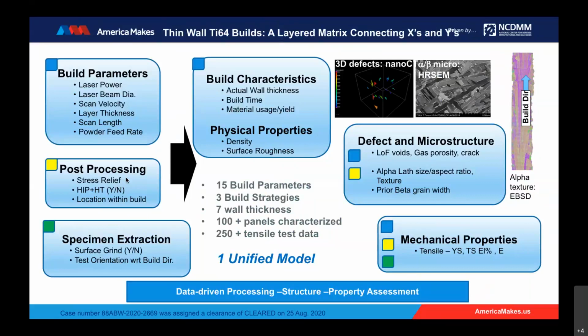And then the last layer down is the mechanical property understanding, which actually takes care of all the above items in the X's, but also looks into the sample extraction, what is the orientation of the sample with respect to the build direction, and also if the surface had a machined surface or not. So all of this together, we had about 15 different build parameters coupled with different build strategies, 100 plus panels characterized, 250 plus tensile tests. And we were able to obtain a unified model connecting the processing structure property assessment via a data-driven approach.